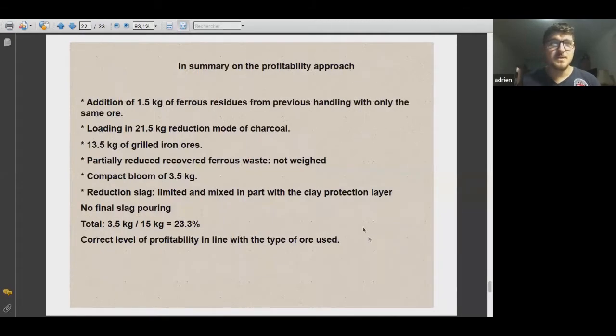To conclude this experimentation: we have 1.5 kilos of residue from a later reduction, so it was already ferrous. 21.5 kilos of charcoal, so this makes 4 bags of 10 liters. 13.5 kilos of iron ore that has been roasted. Some partly reduced bits in the furnace. It happens, but it's not often, that you never stick everything on the bloom. A compact bloom of 3.5 kilos.